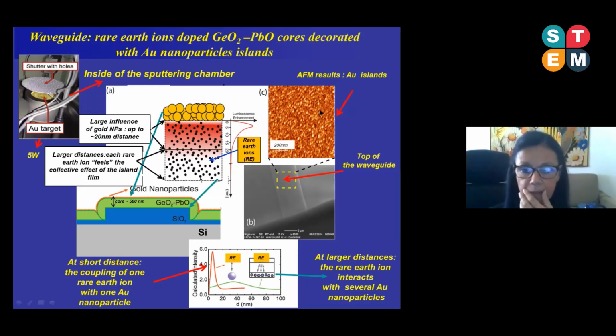And we finally obtained this island of gold. This image was obtained from an atomic force microscope. Normally this island has a height of about 10 nanometers, and the diameter ranges from 10 to 40 nanometers, depending on the process we use.